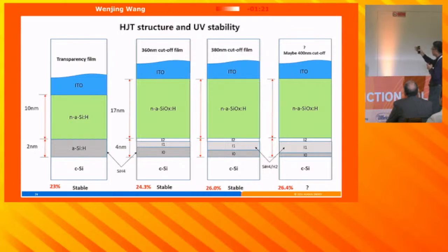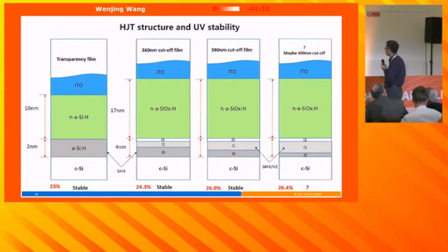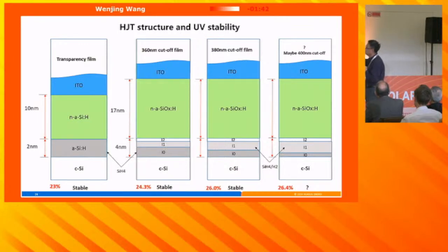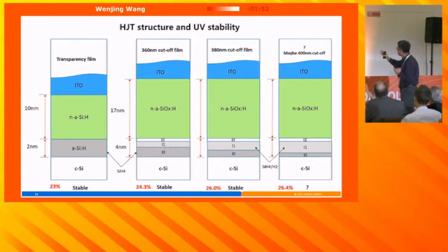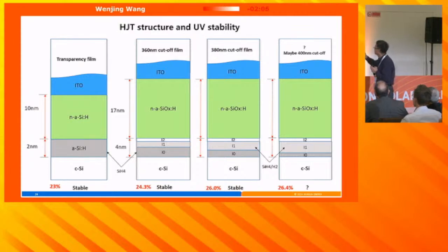But if we further reduce the thickness of the I layer, and at the same time make other improvements, the efficiency arrives at 26%. With that kind of UV cutoff, we can still observe the UV degradation. So we use a UV cutoff thin film up to 380 nanometers, and it becomes UV stable. But recently we further reduced the I layer, and the efficiency further increased to 26.4%. And even with that kind of UV cutoff film, it cannot stop it. There is still some new UV degradation.